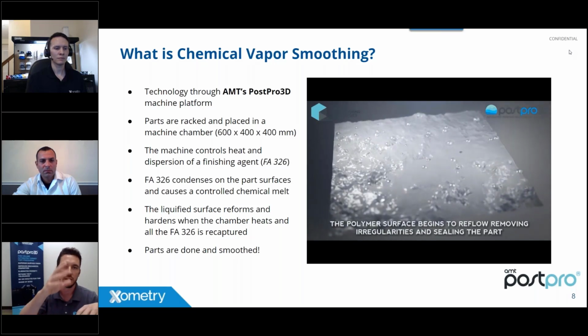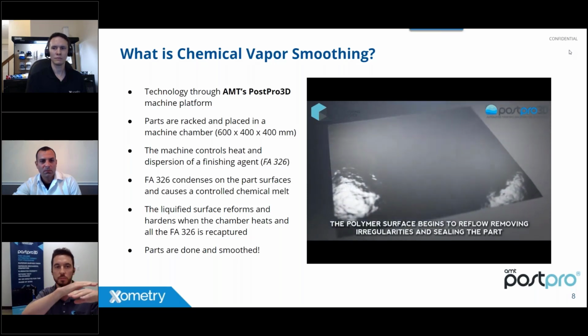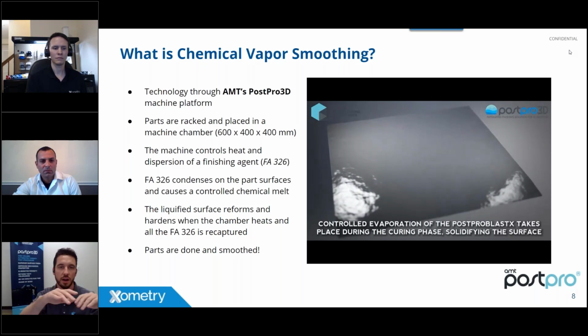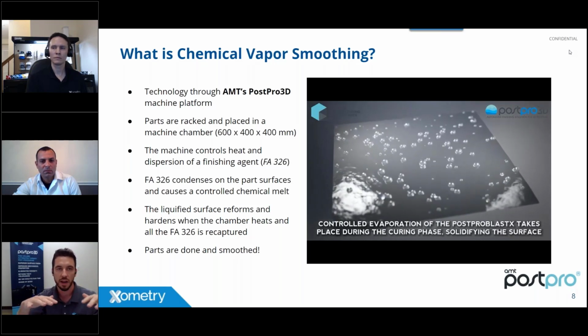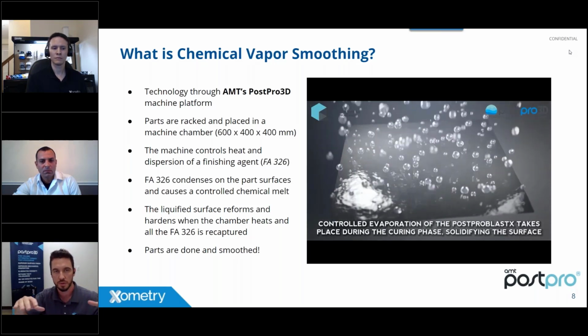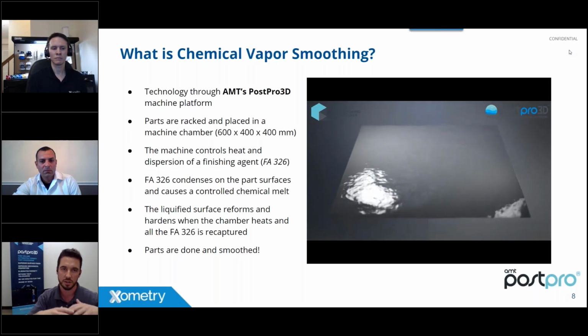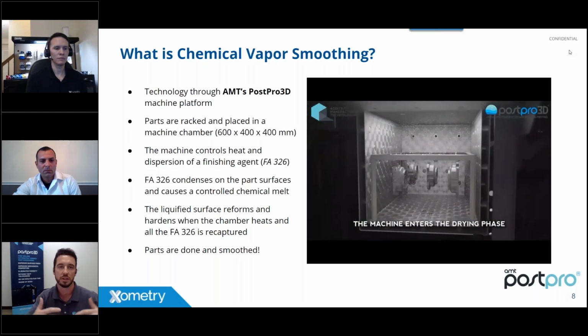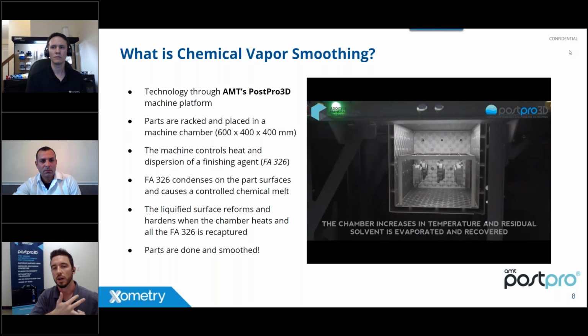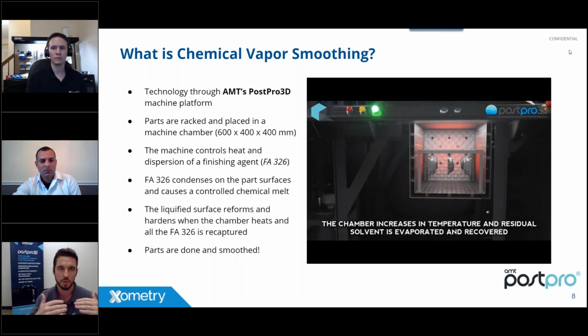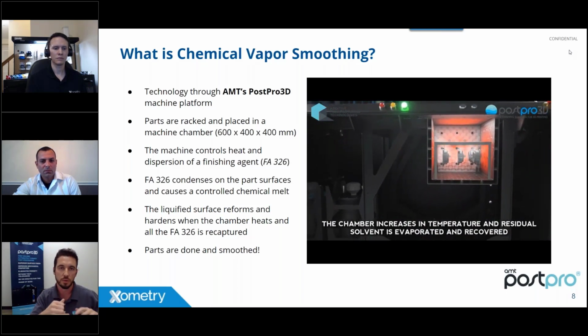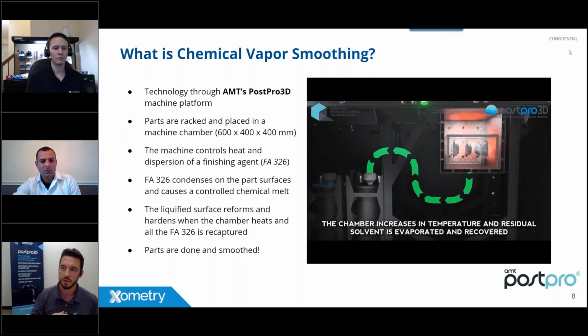And a lot of those peaks that you mentioned are now, instead of being removed or shaved off or sanded down, we're actually moving them down into the valleys, and that's what's making them smoother. And at the same time, we're sealing the surface with that material, whether it's PA11, PA12, ABS, whatever that thermoplastic is, we're smoothing and sealing with that same material.